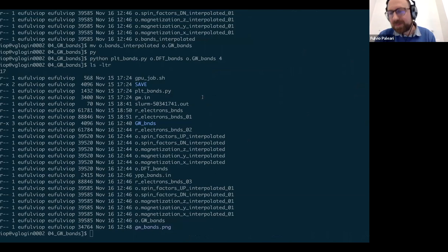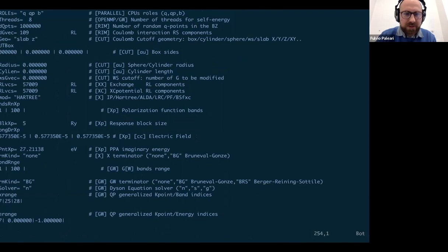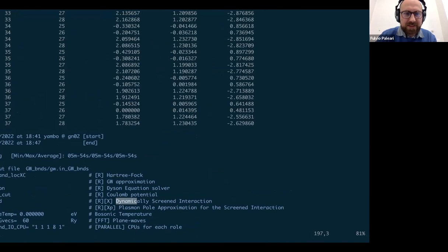If we go there and check the output, we know it is basically the difference between these two. As Ignacio explained, here we have the Kohn-Sham values and here the GW correction. You have to sum 0 and 0.014 for the valence, sum this and this for the conduction, then take the difference. This is the GW band gap in this case. We already know this is the top valence, this is the bottom conduction, and this is where the band gap is. In general this is simple because in a hexagonal Brillouin zone, the K point is always the last point in a traditionally generated Monkhorst-Pack grid. So if you know the gap is at the K point, you just go to the last point.